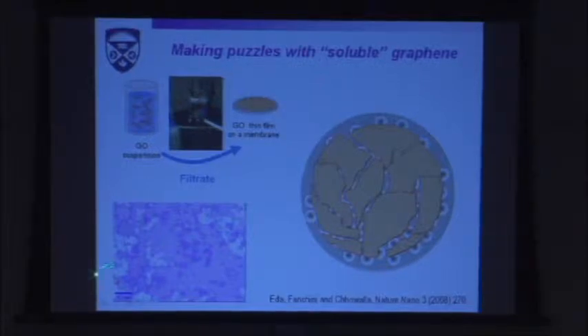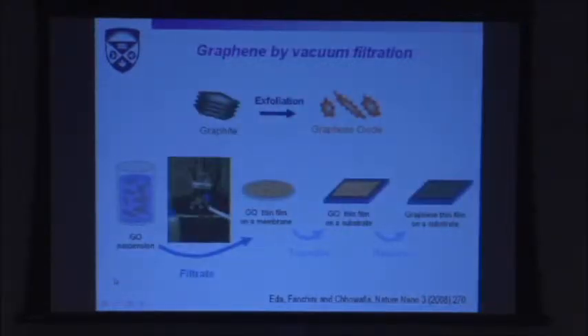So, this is an optical image of what's going on. Here you had a number of few-layer graphene flakes, and thicker graphene flakes. You can make a pretty good layer of electronic grade material. And that's what we did in 2008 when we started to work with graphene oxide.